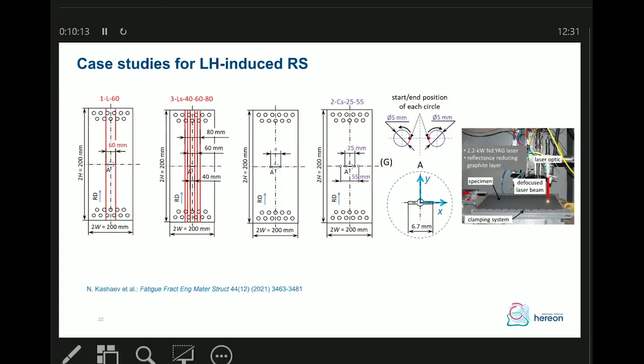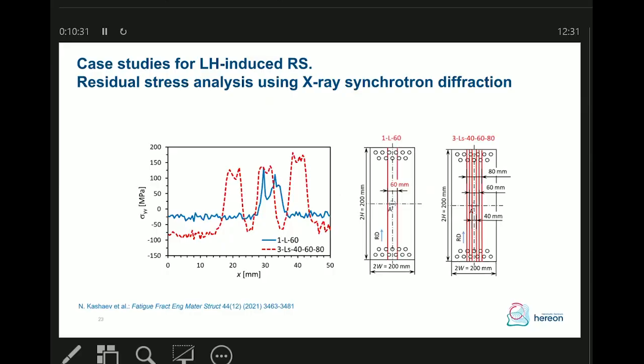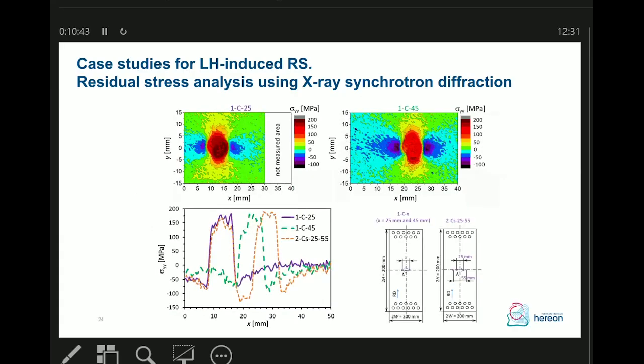Next slide. And for laser heating, we investigated the CT specimen geometry and different application cases, where we apply laser heating lines or just circles in front of the central track. Next slide. And here are the residual stress profiles, also determined using high energy X-ray diffraction, for the cases with laser heating lines. Next slide. And here are the residual stress maps, also identified using X-ray synchrotron diffraction. And here are the profiles for the case where laser heating was applied as circles.